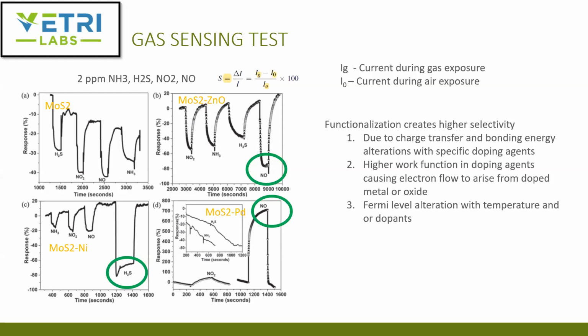So the A figure there, which is just molysulfide, doesn't really show clear separation in signal between these gases. They take it from air, which is at 0% response, and then they put in hydrogen sulfide where the response goes to -30. The way they define the response is the delta current over the initial current. Delta current is the current during gas exposure minus I naught, which is the current during air exposure. We know I naught because they've already established the VI curves for each of these materials. So that's a given. The IG is just the current during specific gas exposure.